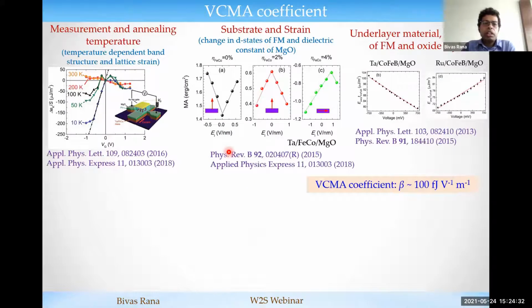So that means if you change the temperature of the system, or change the annealing temperature, you can observe either linear or nonlinear variation of the perpendicular anisotropy as a function of gate voltage, because that temperature essentially tunes the lattice, clears the lattice strain, and that's how it can modulate the interfacial properties or the Fermi energy of the system. Also, people have shown by theoretical study that if you systematically change the strain, you can significantly tune the behavior of voltage control magnetic anisotropy in this manner.